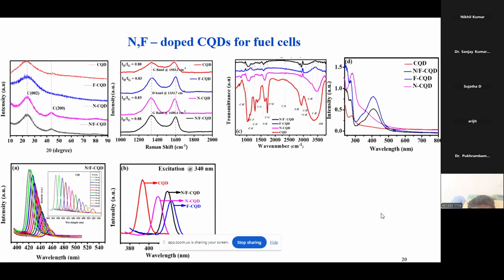We have results where we confirmed this NF doping against pristine CQD, with F doping, N doping, and NF simultaneously. We took Raman spectra for analysis of how the defect structure formed, which varies from the pristine and is far better. Then FTIR shows the functional groups present in it, and the bond formation between C-N and C-F bonding. Then absorbance, we have taken UV-vis. That shows the C=C bond and C-O bond and how it makes the band gap structure. So the luminescence property emission changes.